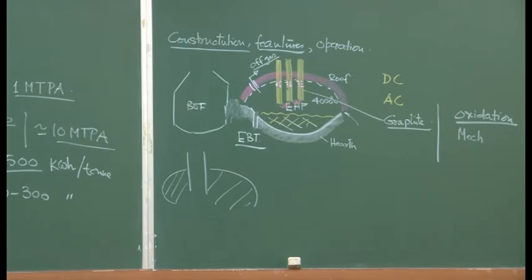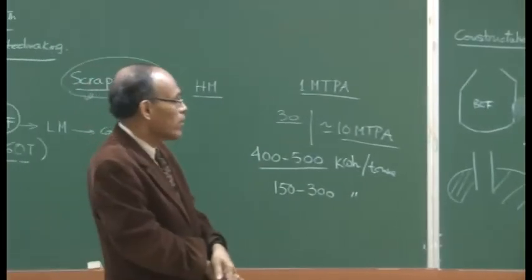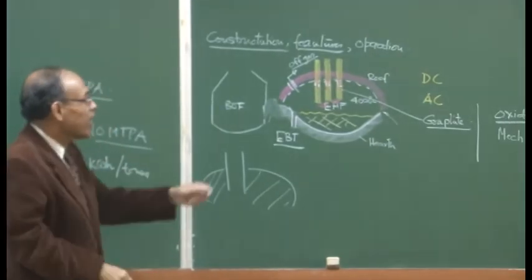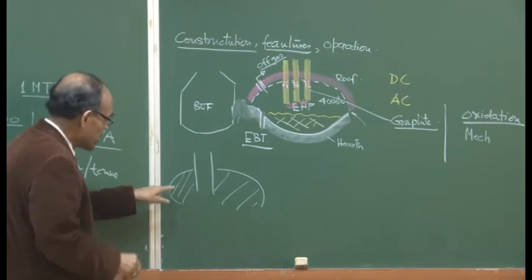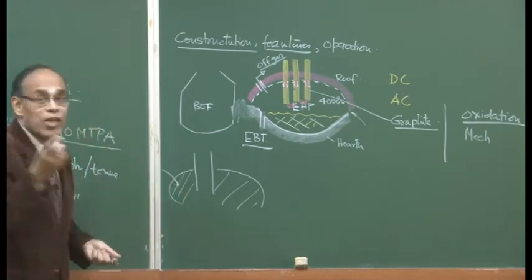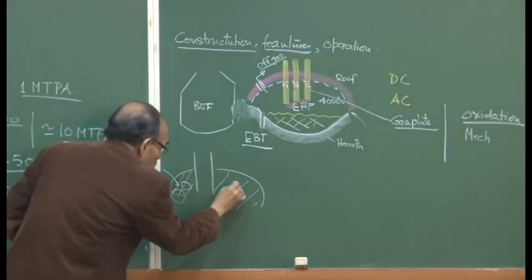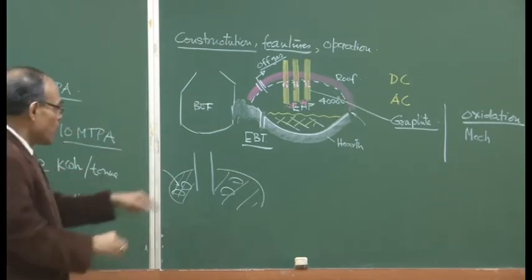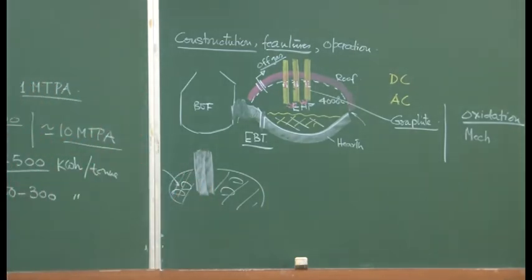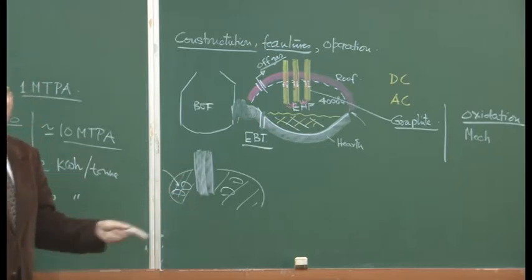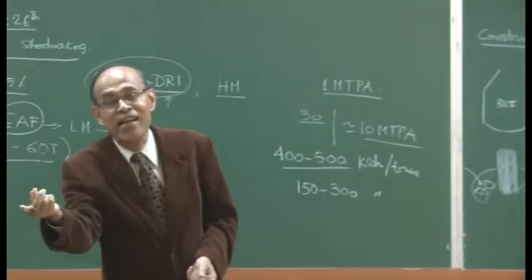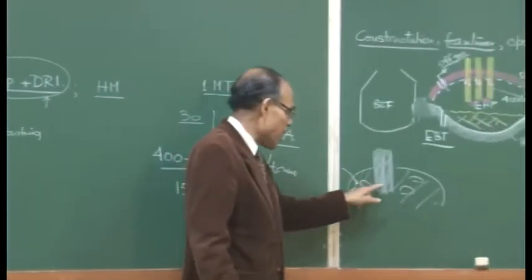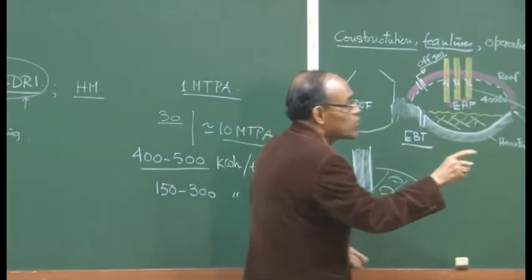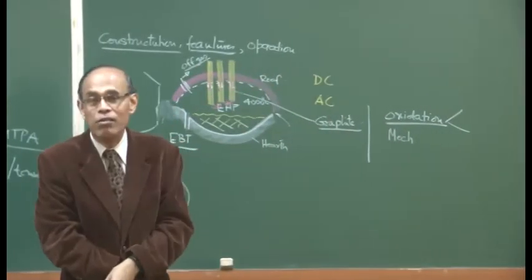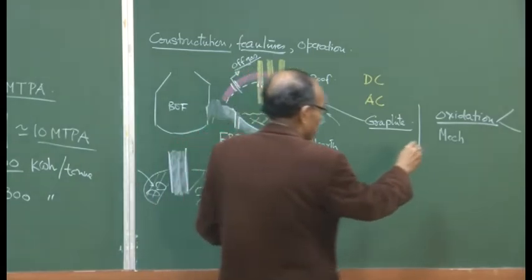Okay? And the moment we put coke into the slag, what happens? Slag contains iron oxide, FeO; we know steel making is an oxidizing process. So, the slag in any steel making process will contain a significant amount of iron oxide, be it BOF steel making or arc furnace steel making. Once we inject carbon into the slag, the slag tends to foam. Why? Because carbon monoxide bubbles are continuously generated. So, there is a volume expansion, and that basically covers up the tip of the electrode, as I have indicated here. Okay. And so the slag also comes in contact, and the same reaction, carbon coming in contact with FeO of the slag and producing carbon monoxide, the slag tends to eat up the graphite electrode. So, the oxidation is twofold basically, with atmospheric oxygen as well as during the foamy slag practice, and mechanical degradation is another.